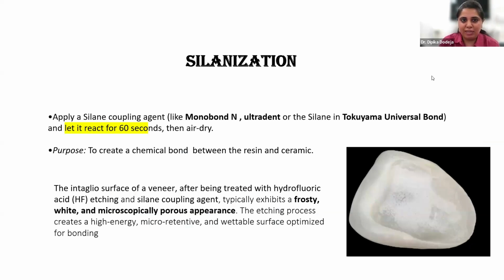You apply a silane coupling agent like Monobond, which is available from Ivoclar, or you get it with a Variolink kit, or you have silane coupling agent from Ultradent. So you apply a thin layer of silane on the entire surface of the ceramic, on the intaglio surface of the ceramic, and let it react for 60 seconds, and then you air dry it. You air dry the silane coupling agent.